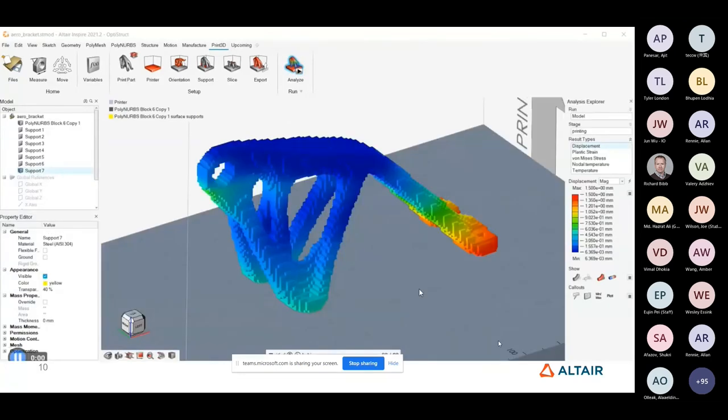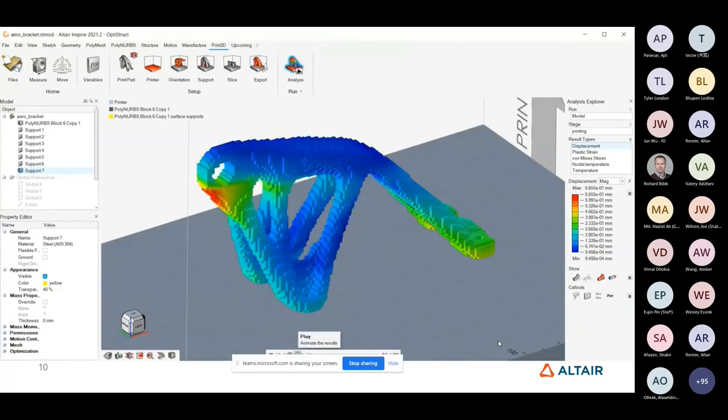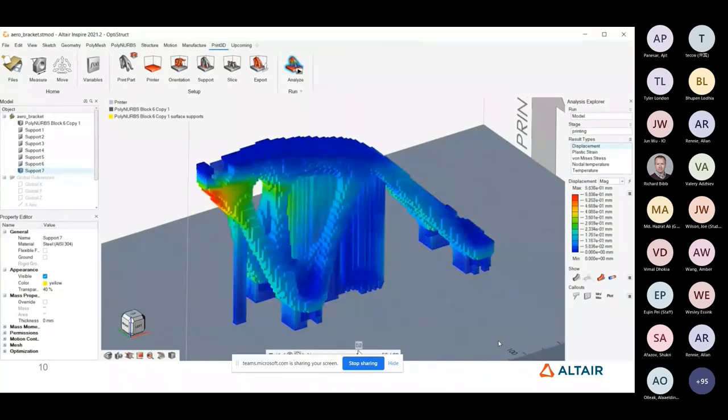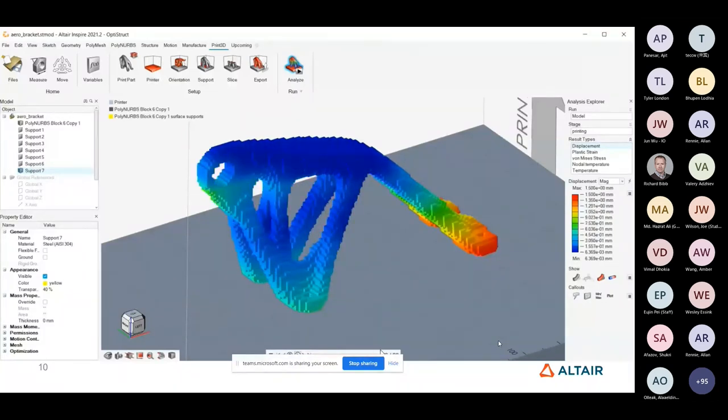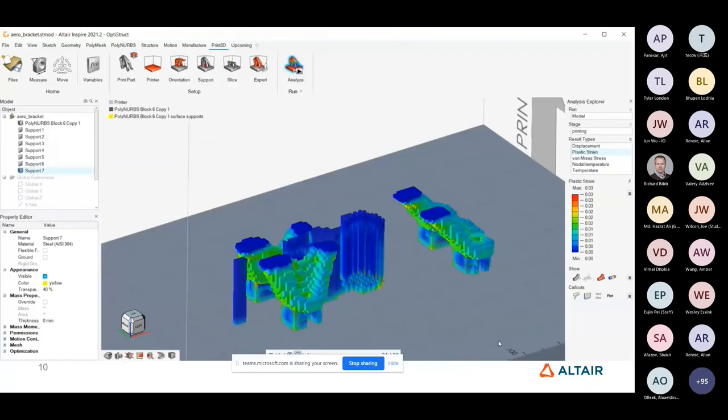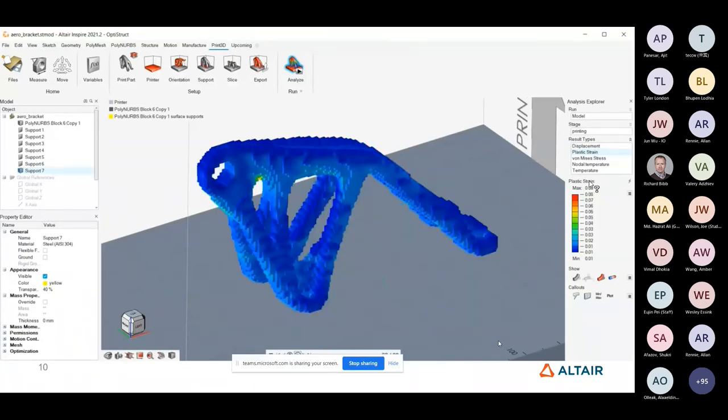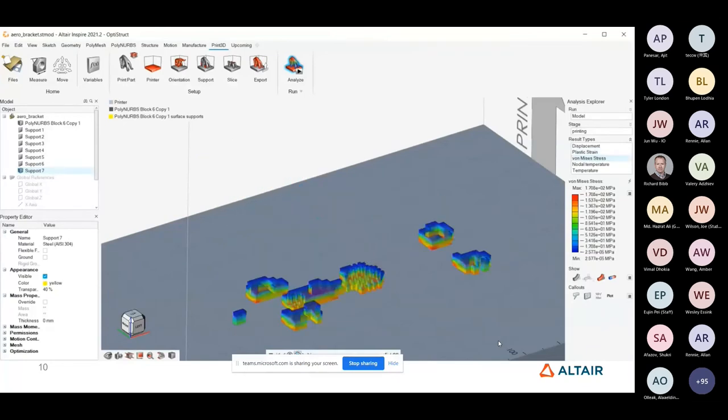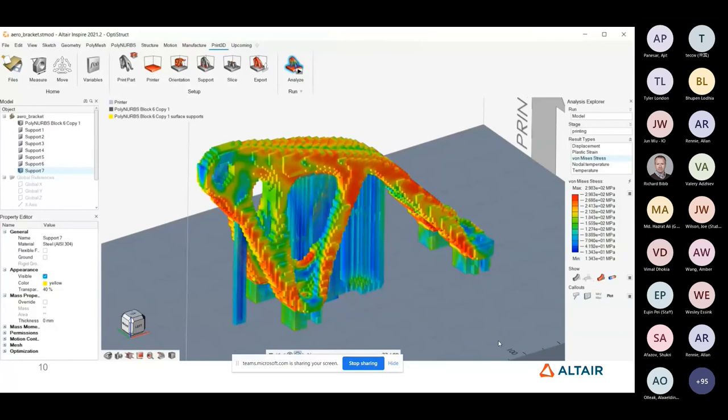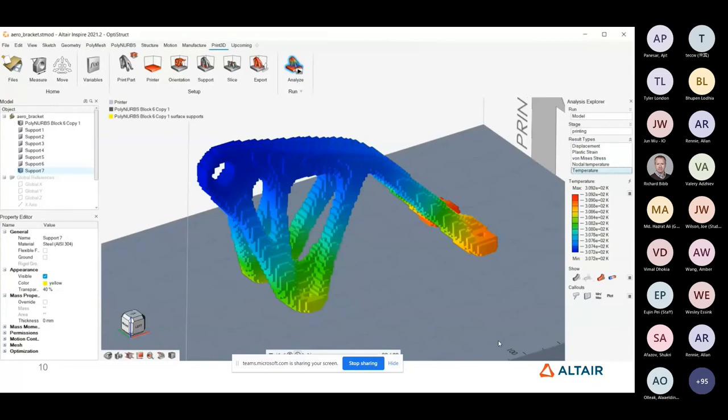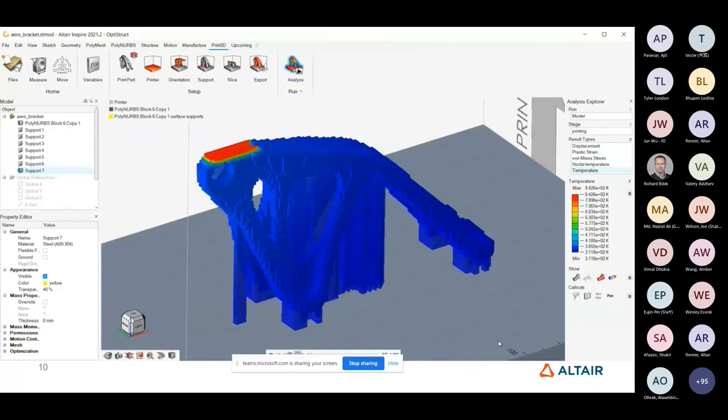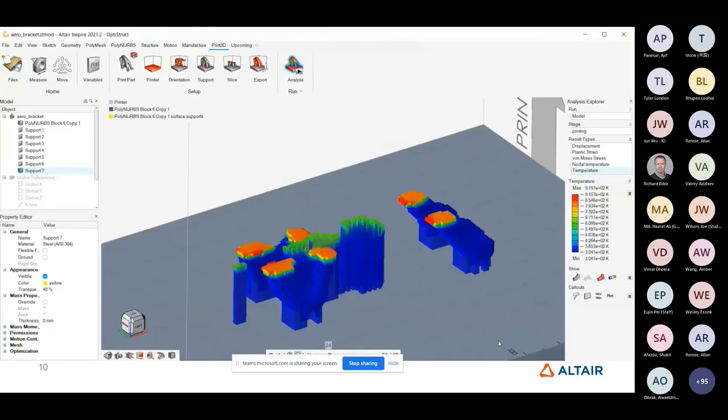So the next video I've got here is showing a different structure in this case. And this is showing the results of the build simulation. So the build simulation comprises the layer-by-layer building that we have here. We then have a cooling step. So I can see I'm just stepping through here. It's obviously the layer-by-layer that we have on here. We then have the cooling step. And then we have the support removal step and the resulting spring back that can take place. And of course, we enable the designer to investigate how the part is deforming, any plastic strains that may be taking place, the stress and strain state in the component.